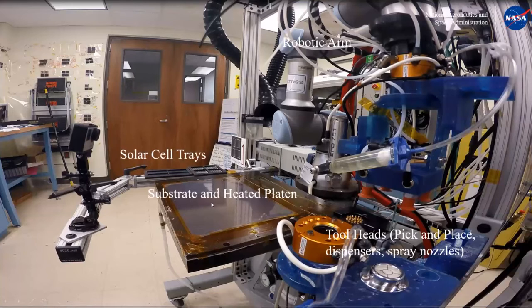And that substrate, we currently start with a roll of polyimide that has a backer on it. But there are options beyond that. We've also looked at spraying your own substrate and just starting with a backer. And certainly there's room to grow there as well.